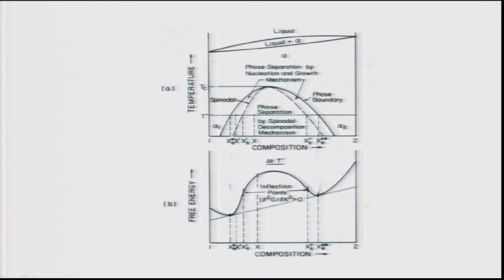isomorphous type phase diagram, which leads to formation of the solid solution alpha. At temperatures above Tc, the alpha is stable, it is a random solution. At temperatures below Tc, it undergoes spinodal decomposition, and everything is shown here. The inside curve is known as the chemical spinodal, because that is where the transformation will happen via spontaneous decomposition, with no need of nucleation.